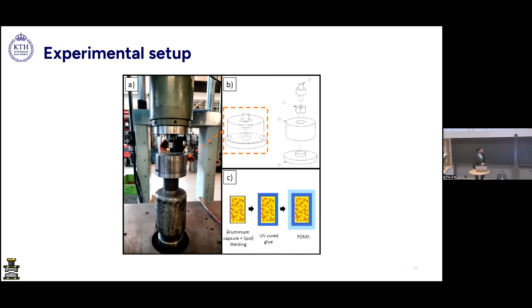This was the experimental setup that we developed at KTH, and we have a hardened piston at the top, which is pushing the sample inside this experimental jacket. The sample itself was contained inside an aluminium capsule, which is spot welded to avoid any leakage. On top of that, we had a UV cured glue, and on top of that, a PDMS coating, all to ensure a smooth pressure transfer in the system. If you have a hard metal to hard metal contact, there might be a chance that you break the system and the capsule. This was just to ensure uniform and smooth pressure transitions.